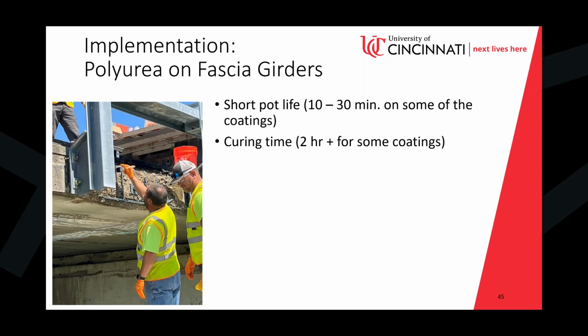It said 10 to 30 minute range on some of the coatings. It would start to get pretty tough to be able to paint. And for some of them, honestly, it happened closer to 10 minutes. So you have to mix really small amounts and work kind of quickly. And so that's a challenge, not so much a challenge in this small area, but if you were going to larger areas, you'd have to do lots of small mixes before the material would set up.